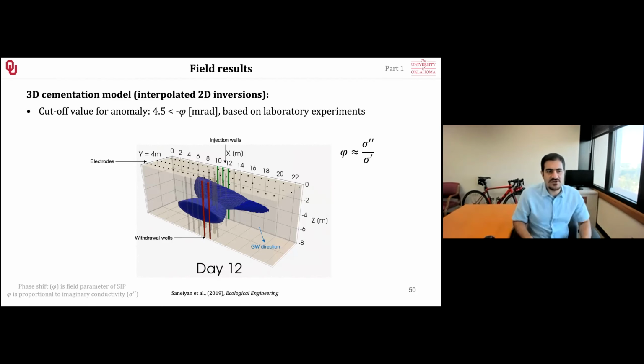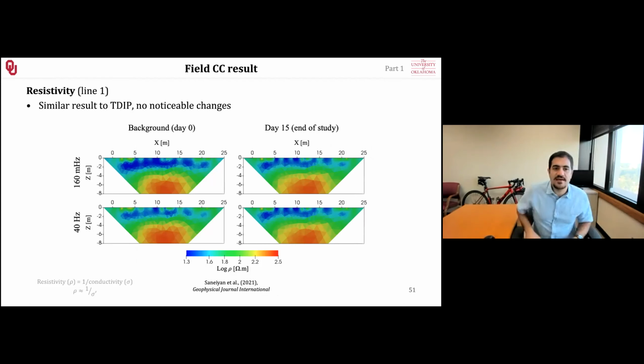Our SIP measurements were similar to time domain. The real part of the spectral IP did not show any changes over time, only showed the structure of the subsurface as expected because we didn't change any conductivity.